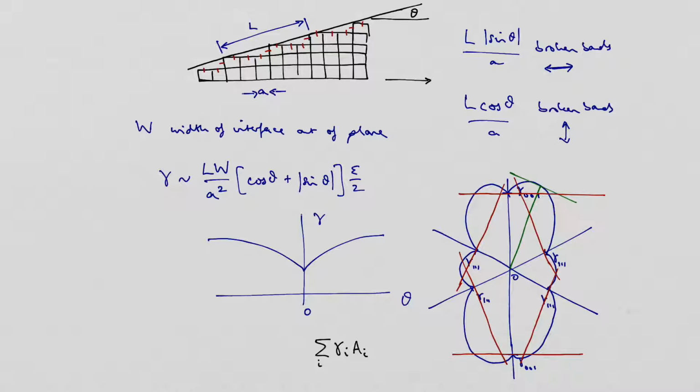So sodium chloride. What are the lowest energy surfaces of sodium chloride? See salt crystals? 100, because they're the charge neutral ones, right? It's an ionic crystal, so you can't start creating surfaces that just have chloride ions in them. You're not going to get any of those. You have to have the charge neutral ones.